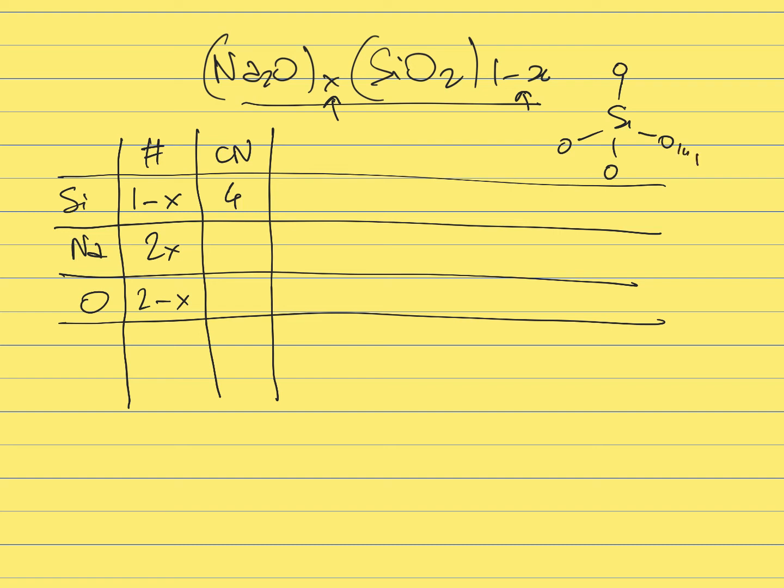And whenever you have sodium, it's going to form some non-bridging oxygen. Every time you add one sodium, it's going to form one non-bridging oxygen. So this is an NBO here. So the number of NBO in the glass will be equal to the number of sodium.